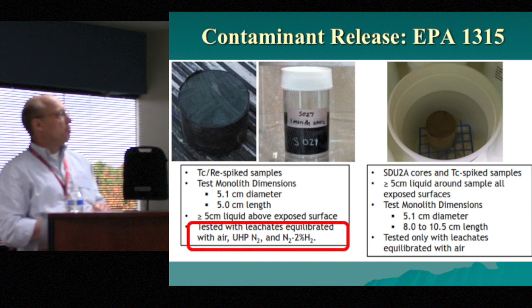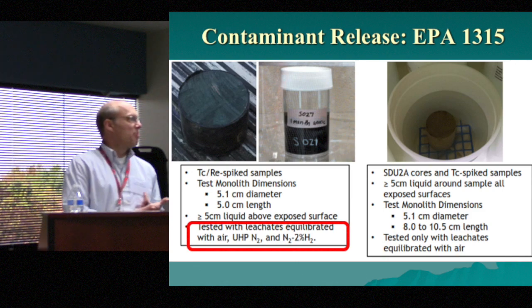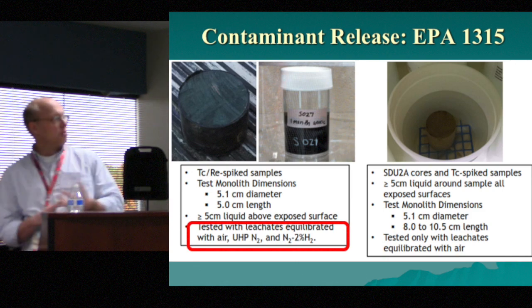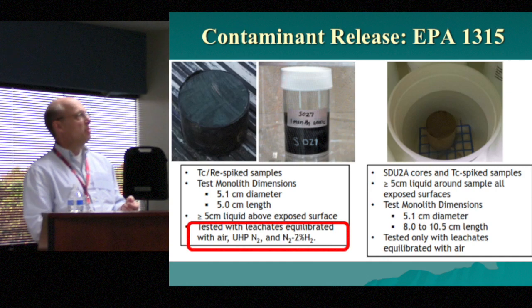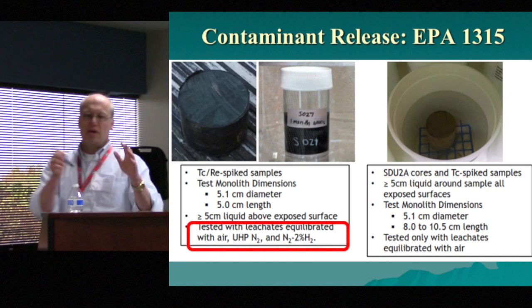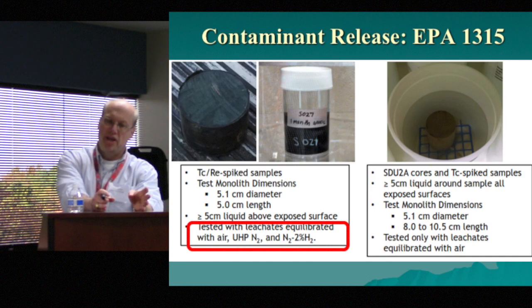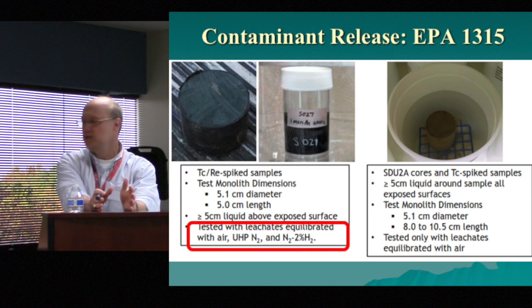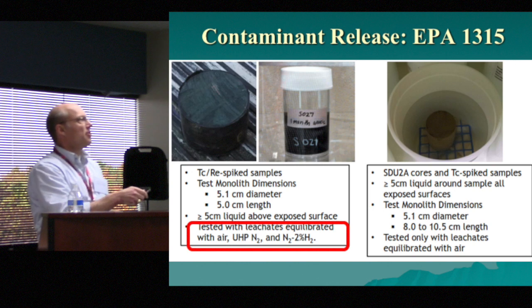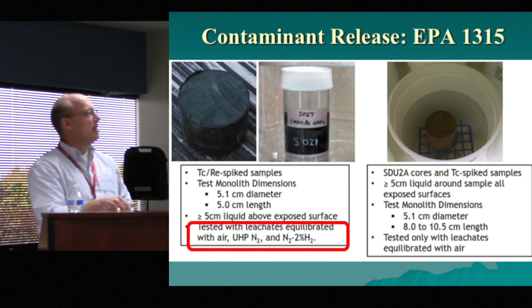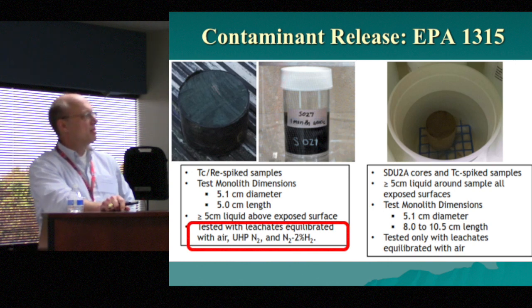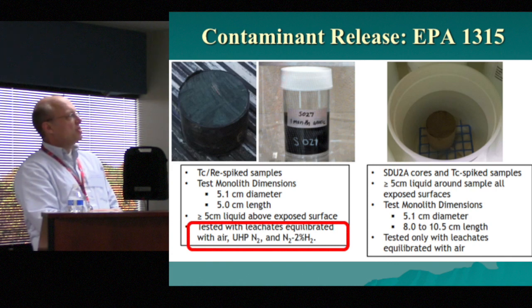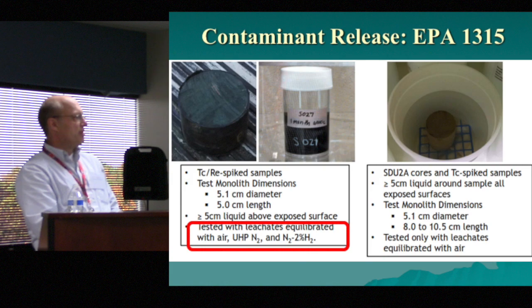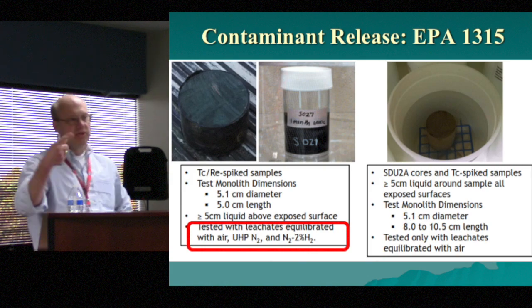The next step that we did, and this included both spike cores and SDU2A cores, is we did the 3D tests in which you measure all of the surface area associated with the intact part or monolith, and again you put it in solution for various amounts of time. When we start looking at some of the results, though, it'll be clear why we only did this in air for this second test. Next slide.